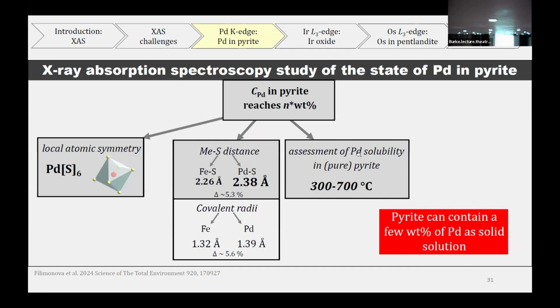So in a nutshell, this paper is already published, and the concentration of palladium in pyrite was quite high, a few weight %. We proved that it's a solid solution. The big palladium atom, of course, expands the first coordination shell, and the expansion is proportional to the difference between the values of the covalent radii. And we also performed the assessment of the palladium solubility in pure pyrite.